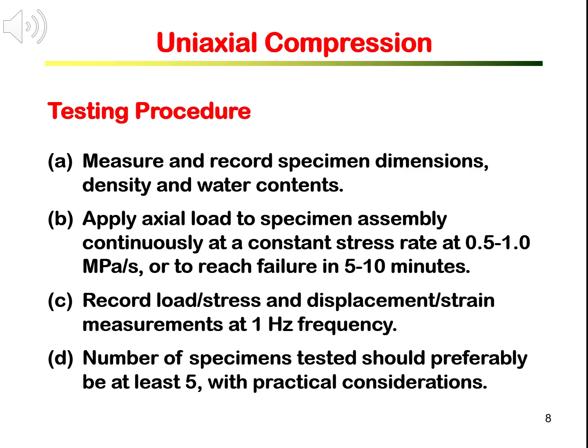While we apply loading, record load, stress, and displacement or strain measurements at 1 Hz frequency. Stop the test after failure or after the peak stress, if the test is not planned to obtain the post-peak stress strain curve. For tests to obtain the post-peak stress strain curve, we will explain the procedure on the next slide. The number of specimens tested should preferably be at least 5, or as practical considerations allow.